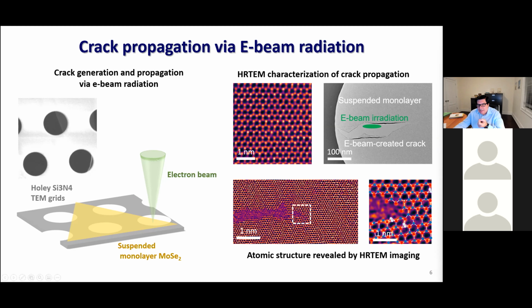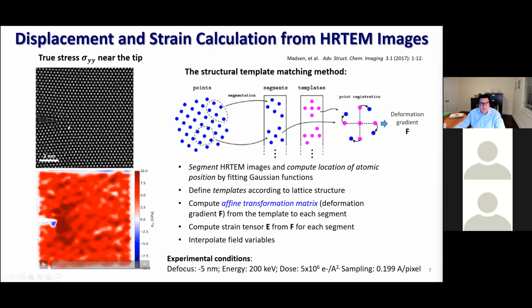That's the information, but there is more that we can gain, which is the computation of the strain fields at the crack tip, and using that together with some constitutive law to compute the J integral. What you see here is an image where the atomic configuration is revealed in the CCD camera for a certain magnification. Then, using an algorithm called the structural template matching method, the idea is that you break the image into segments and then map each to a template. The template is an image of an undeformed lattice. You can think of the template as the reference configuration in a continuum mechanics fashion, and the image, the actual image of the atoms, as the deformed configuration, such that you can define a mapping and compute the deformation gradient everywhere in your domain.